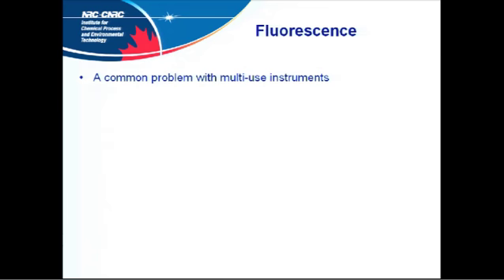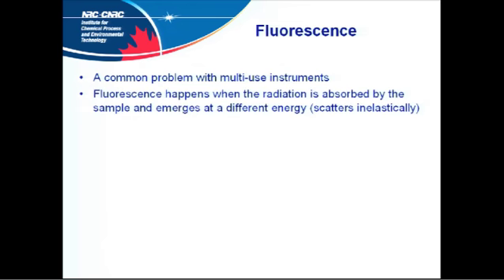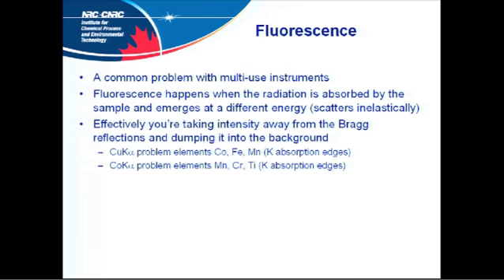Now, fluorescence. This is a particular problem with multi-use instruments. You probably already know this effectively happens when the radiation you're using is being absorbed by the sample and re-emitted. So what you're effectively doing is taking intensity away from your peaks and dumping it into the background. It's taking away what you want and putting it where you don't want it.